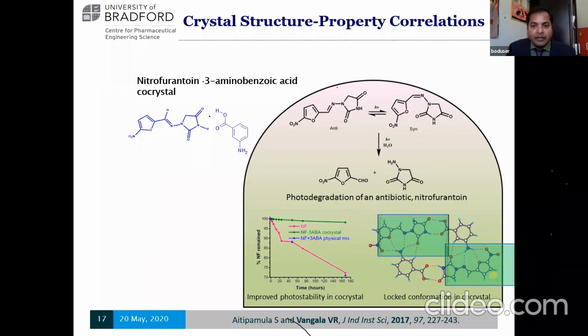isomerization. If you see, this is the C double bond N, this is the labile group, which is converting. There is a very rapid conversion from cis to trans to cis. Trans is the most stable, and that is the commercial form. This is followed by hydrolysis, and you can see furfural and hydantoin. So this is mechanistically how nitrofurantoin degradation is taking place.